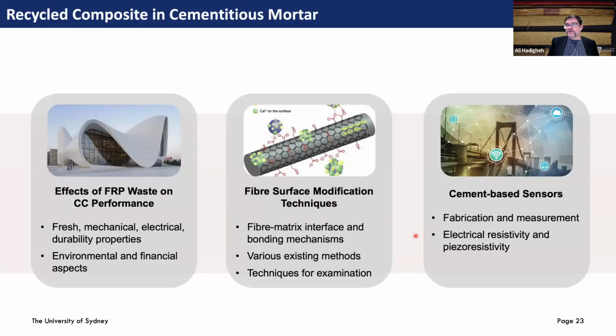We started working on three aspects of it. Basically, we started off with looking at how this FRP waste performs when we incorporate it into cementitious material, and what the durability and the performance of the mechanical properties would be. But at the same time, we have issues related to fiber dispersion, so how we can improve that performance. But also, when we are talking about carbon fiber and cementitious composites, this is always very tempting because they are conductive materials. They have sensing properties, they have electrical properties. So self-sensing and using them as a sensor in concrete is also tempting. So that's why we looked at these three major aspects.